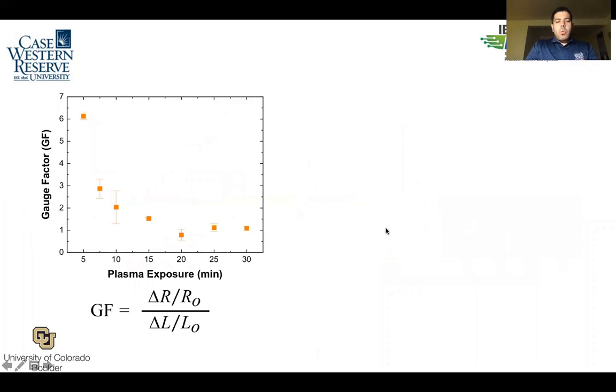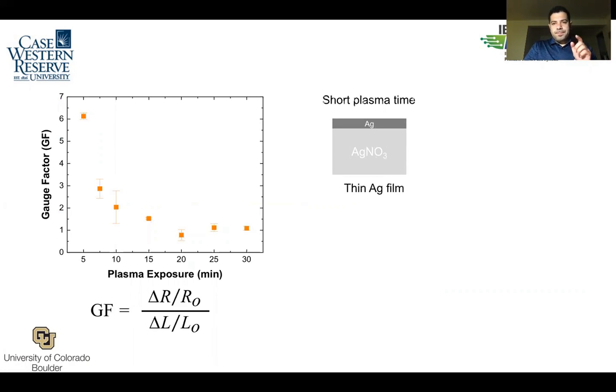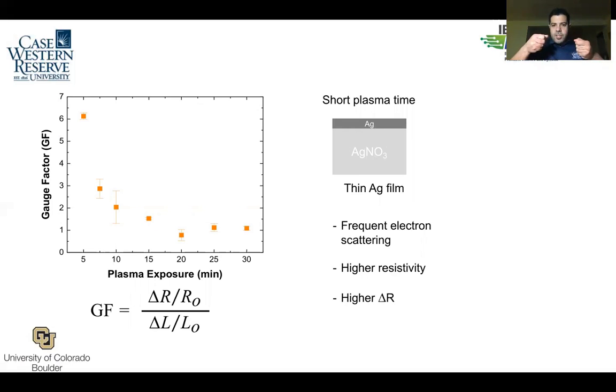So you may ask a question, what's the science behind that? Why did the gauge factor decrease as we increase plasma exposure? For shorter plasma exposure, you have a thin silver film. When you have a thin conductive film, you do increase electron scattering. That contributes to the total resistivity of your sample. You get a higher resistivity. Higher resistivity means when you stretch the sample, you'll get a higher delta R, and that translates into a higher